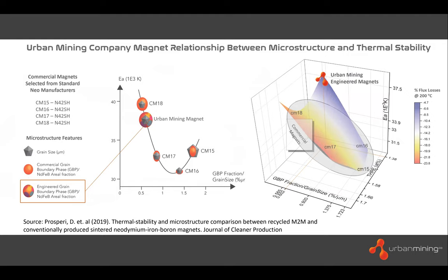So let's look at this chart to illustrate this with data, right? Going from left to right, we're looking at four different commercial grades of magnets. That's N42SH, four different commercially provided magnets, all with the same grade, okay? All N42SH type grade material as defined by those particular suppliers. And then we did an analysis across a bunch of features. So microstructure features, looking at grain size and grain boundary phase ratios. And then we looked at composition. Essentially what we were able to identify first is that there was a range of grain size produced by all these varying suppliers, Urban Mining included. And there was a ratio of grain boundary phase that everyone had, right?